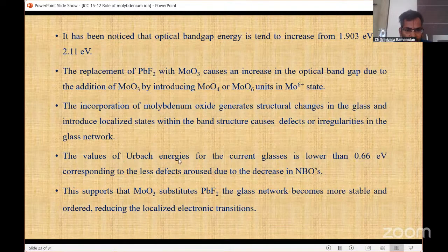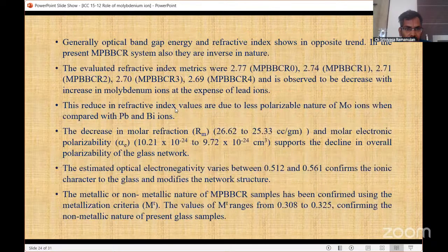The Urbach energy is around 0.66, which corresponds to fewer defects in the glass network that is forming, because of the decrease in non-bridging oxygens. The refractive index is changing from 2.77 to 2.69, a decreasing trend. There is a decrease in the molar refractive index from 26.62 to 25.33. Electronegativity also changes from 0.512 to 0.56, which is increasing, and this says the ionic behavior of the glass increases because of the modified network structures.